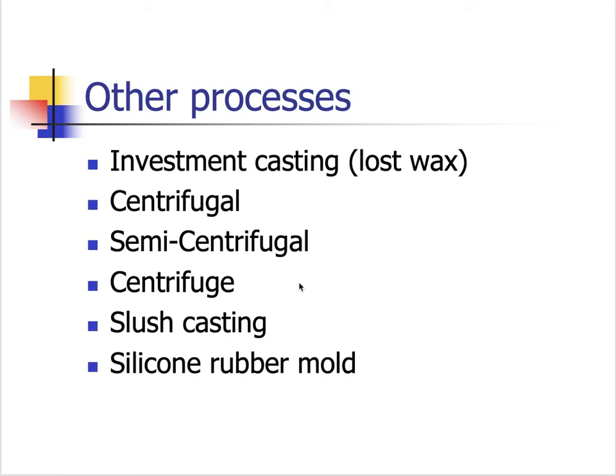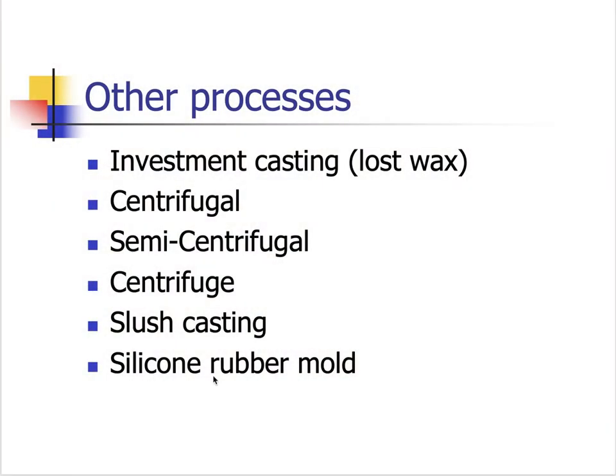Okay, some other processes that I'm going to explain briefly, but I'll put some videos up on these. Investment casting, where we take a wax part. Essentially, usually they have an aluminum mold. They inject a wax part into it. That wax part cools, pops it out. So it looks just like a plastic mold, right? So you just molded this plastic thing. Wax is not very much different than plastic. So now we have this wax that's the shape of the part that I want, but it's a little bit bigger because remember that pattern shrinkage stuff? The metal shrinks. Then we attach it to a sprue and we dip it in a ceramic. And that liquid ceramic coats the outside of it. And we do this like 10 times so we get this nice thick layer of ceramic on the outside. You melt out the wax, you pour in molten metal, and now you got your casting. So that's the long and short of investment casting.